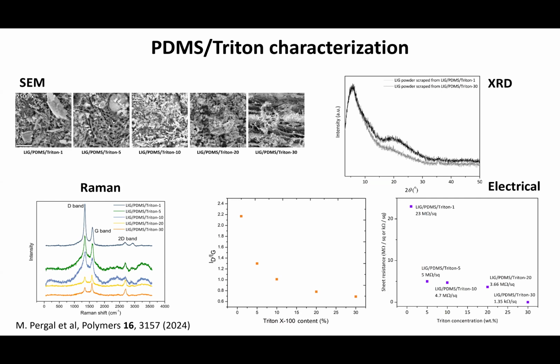30% Triton in this compound is better than 1%. Then looking at Raman, at the bottom in the middle, you see, for example, the ratio of the defect peak intensity to the G peak intensity, so ID over IG, decreases as you add more Triton, which is again an indication that you get higher quality graphene from adding Triton. And the same trend is repeated if you look at the bottom right, this is sheet resistance measurements. You see that the sheet resistance will decrease as you add more Triton to the PDMS matrix and you optimize laser parameters to form LIG. And you get down to about 1.3 megaohms per square, which is not the best for electronics, probably, but it may have some other uses.